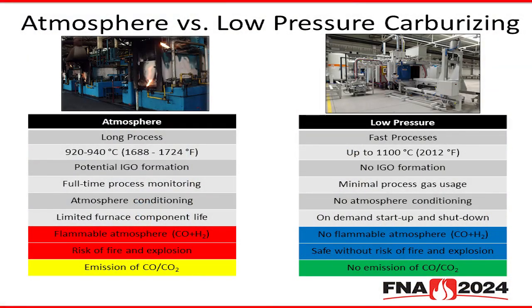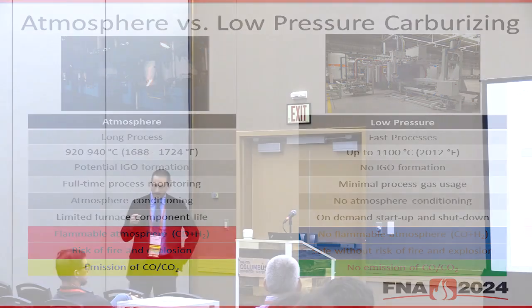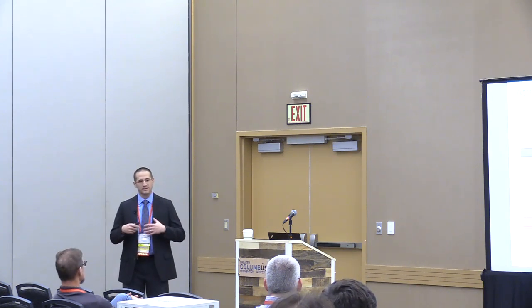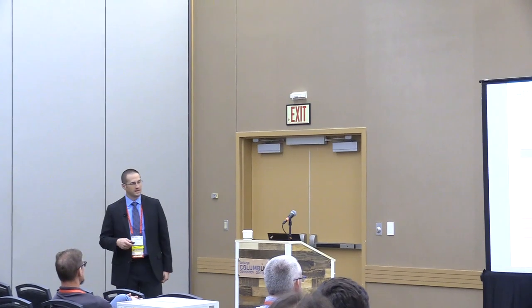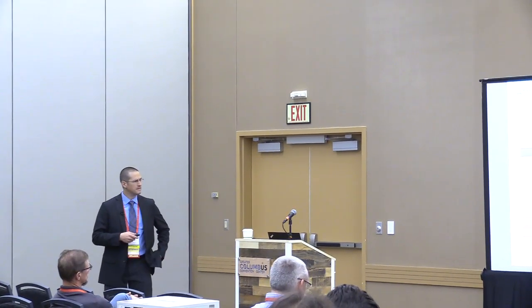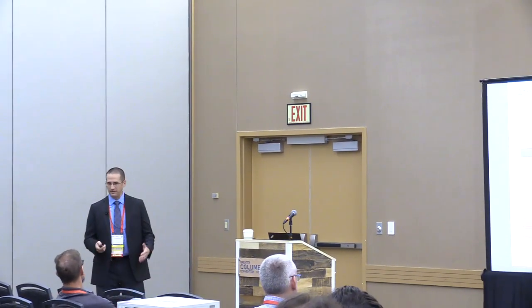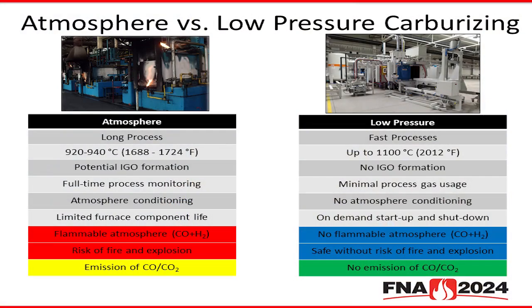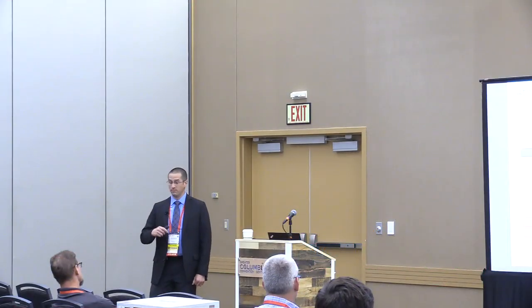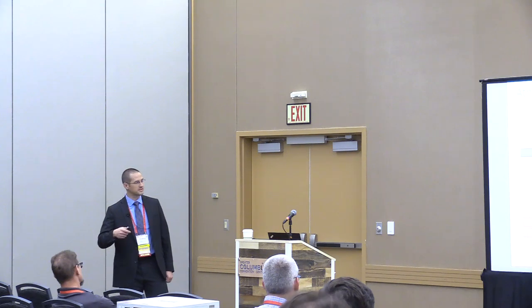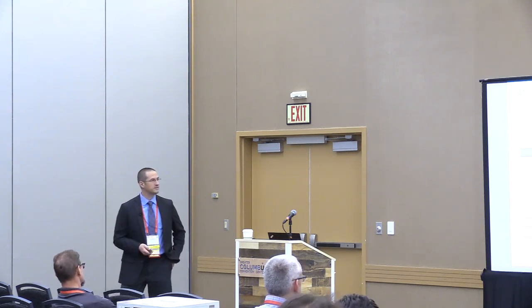To maintain a quality atmosphere, the furnace typically needs some conditioning prior to the process and requires continuous process monitoring. Also, because we're doing this at atmospheric pressure, there's always the opportunity for some oxygen infiltration and therefore potential for IGO formation. And because we continue to run the furnace all the time, as a matter of course, we have some effect on the furnace component life. From a safety perspective, of course, too, there's also some risk in that it's a flammable atmosphere, and because of that, there's risk of fire and explosion. But moreover, and which is becoming a more popular discussion today, is the emission of CO and CO2, which I will come back to in a moment.